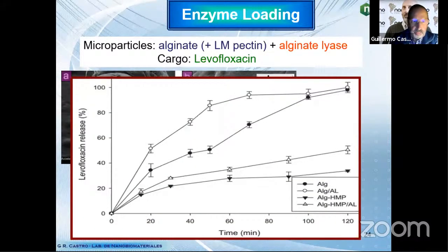And when we study the release of levofloxacin, we can see that the presence of alginate lyase in the structure of the microparticle changes the release. In both cases, they enhance the release in the first, I would say, hour and a half. This is very interesting because in this case we can regulate the release of levofloxacin just by changing the alginate lyase concentration.